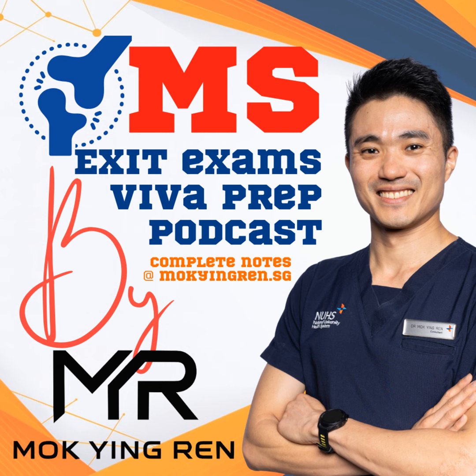Makes sense. Now, the notes bring up an interesting point. Why not use XLPE in total knee replacements? That's where things get a little controversial. While XLPE has been a game changer for hip replacements, there's some debate about its use in knee replacement. What are the concerns about using it in the knee? Well, first of all, the material properties change after cross-linking, as we talked about. XLPE can become more brittle and less resistant to fatigue, and that's a bigger concern in knee replacements because the forces and movements are different compared to hip replacements.